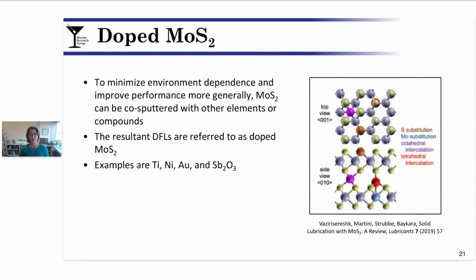So how do we mitigate this? One approach to mitigating the adverse effects of the environment and more generally improving the performance of MoS2 dry film lubricants is through the use of what are called dopants. These are elements or other compounds that are introduced into the MoS2 during deposition or synthesis. There have been a variety of different elements explored for space DFLs, including titanium, nickel, gold, and antimony oxide.